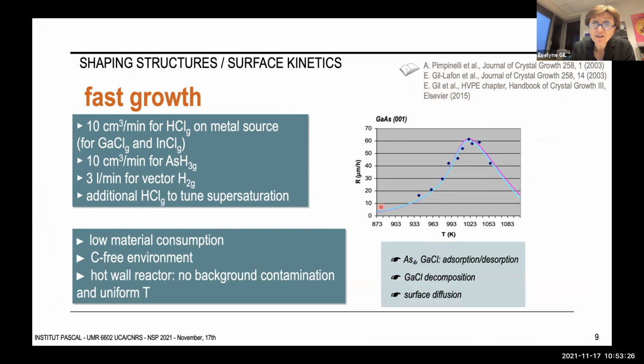So if you now go back to the variation of the growth rate of III-V epilayers with the temperature, this variation features a growth regime limited by surface kinetics on the low temperature side, and the second one at high temperature governed by thermodynamics. Of course, thermodynamics simply foretells sublimation of the solid where the adsorption of gallium chloride species does not occur anymore. And the growth regime at low temperature is very interesting because it is limited by the kinetics of each of the surface elementary steps. Adsorption and desorption of molecules transporting element 3 and element 5. Then decomposition of these adsorbed molecules, and the limiting one is the chlorine decomposition and further desorption of the chlorine atom. And finally, the kinetics of the surface diffusion mechanisms.